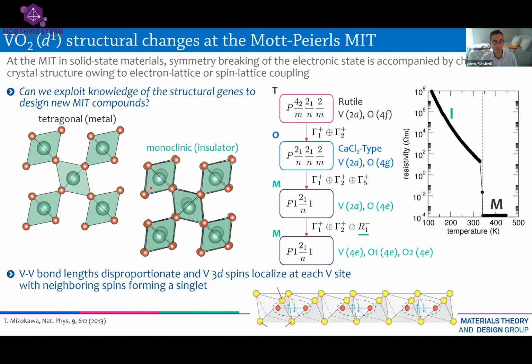If I take one of these chains, turn it on its end, you can see what happens. These two vanadium get closer together, and these two vanadium are further apart. So these two are closer together, these two are further apart, and these two are closer together. This is a type of distortion in the structure that's permitted by the one-dimensional chain of the rutile structure. So it's a very special rutile structure. And what happens then is that this vanadium decides to make a chemical bond with this vanadium, and they each share one electron.